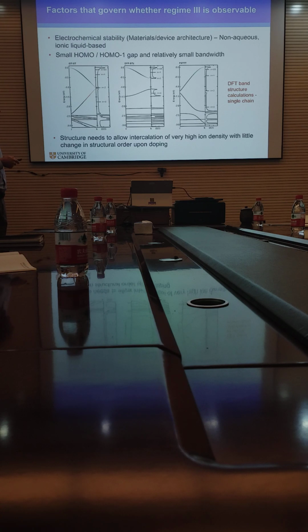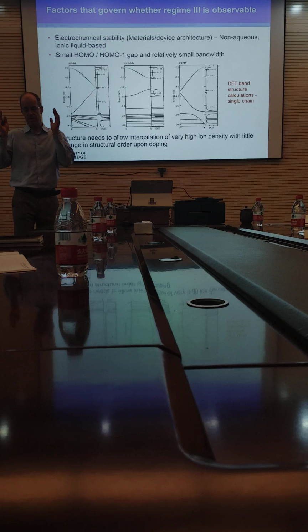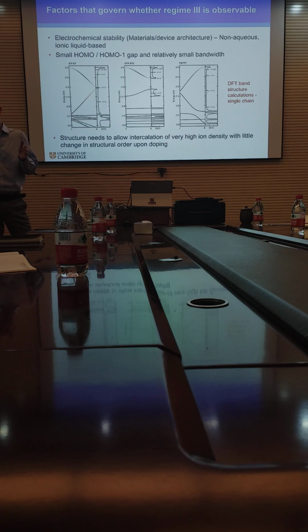In PBTTT, in principle, the HOMO -1 band should be accessible. It's quite close to the HOMO level. But the problem that we have in PBTTT is that this structure where you have one charge per repeat unit is actually energetically very stable. So you have this interdigitated structure with one charge per repeat unit, and we find it very difficult to push more ions into that structure. We just can't charge PBTTT to higher charge density.